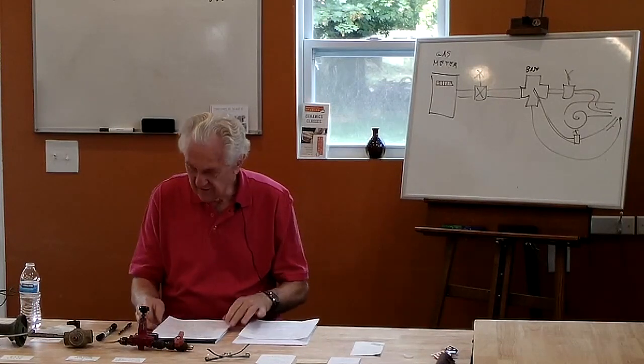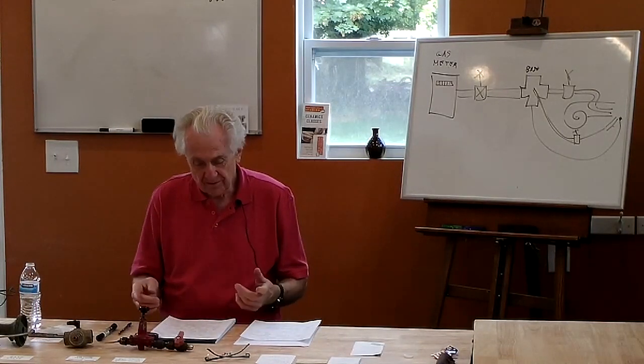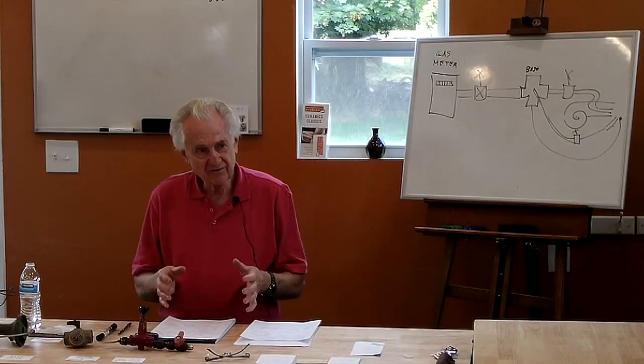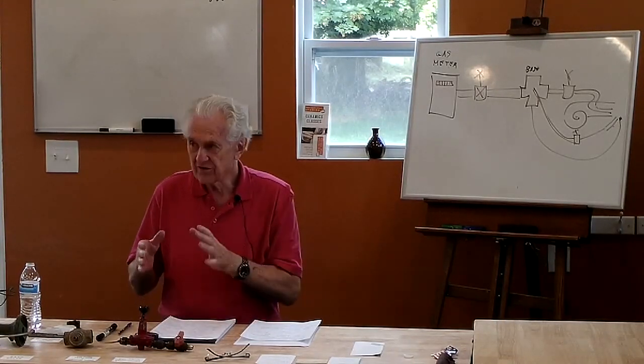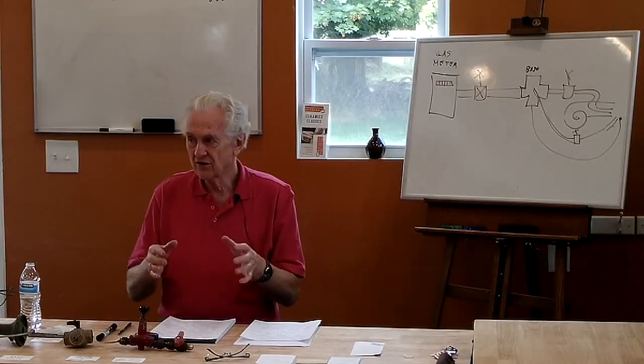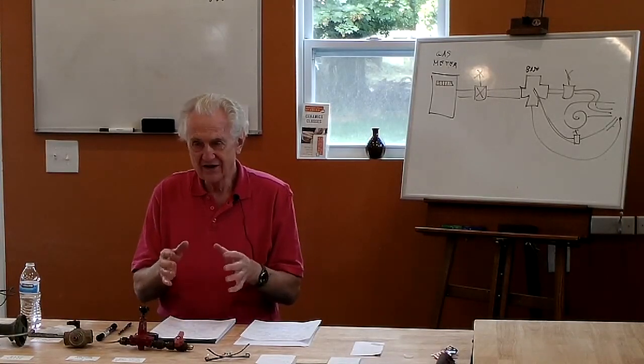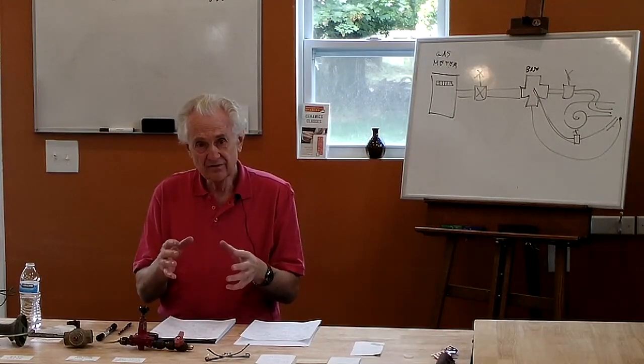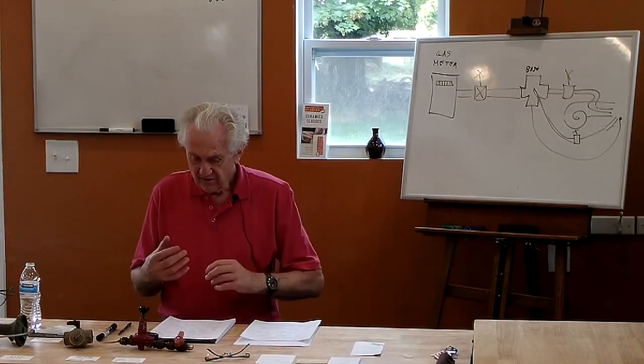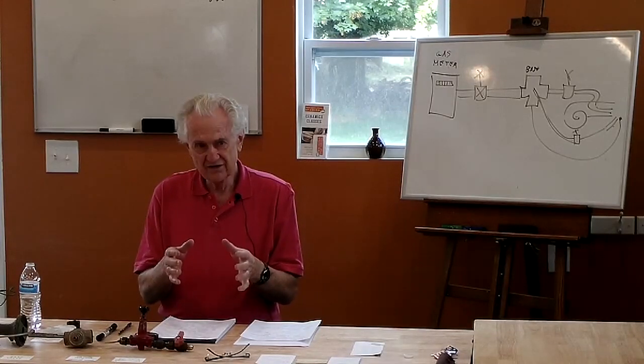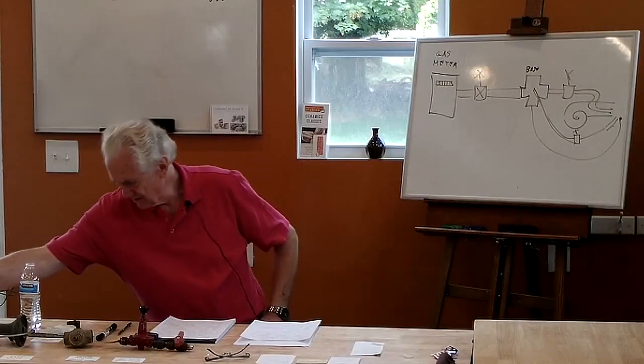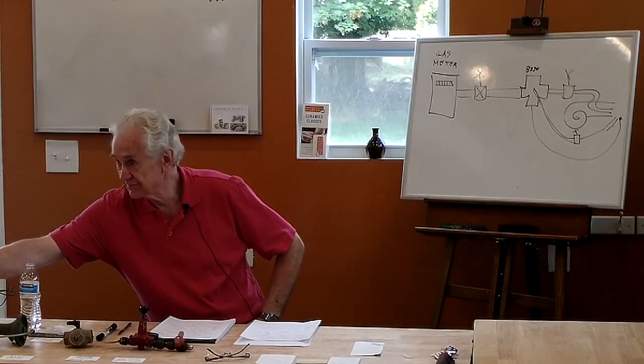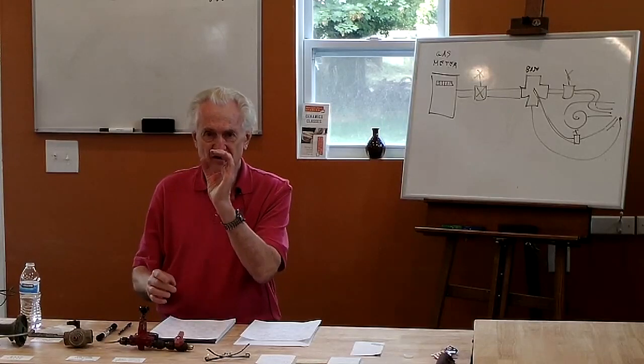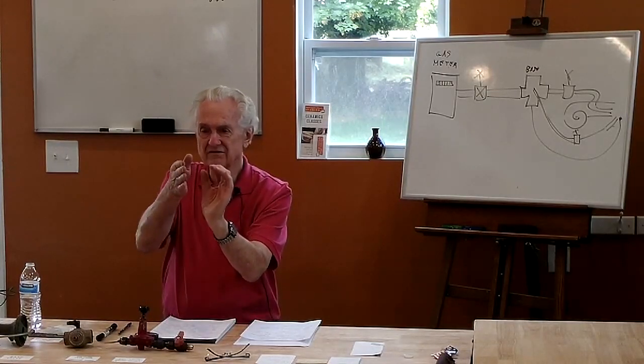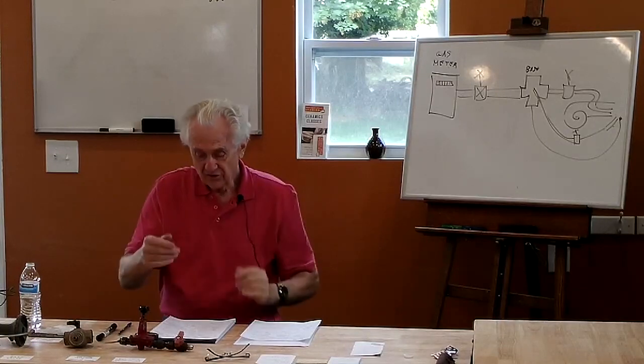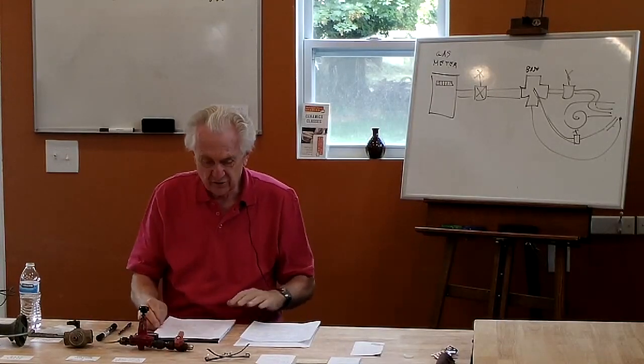Another feature with Venturi burners is that, as I mentioned before, it's important to get thorough mixing of all the gas and the air before the ware chamber as much as possible, because I don't want unburned fuel or air hitting the pots. I'd like just the flame and the hot gas hitting the pots. So I need some way to design or set up the kiln so that I get complete mixing. Because the air that's coming into the burner, I'm getting pretty good mixing. But the secondary air, I've got a stream of gas and air, and coming around the outside of it, I've got air. So there are features you can build into a kiln that will help do that.